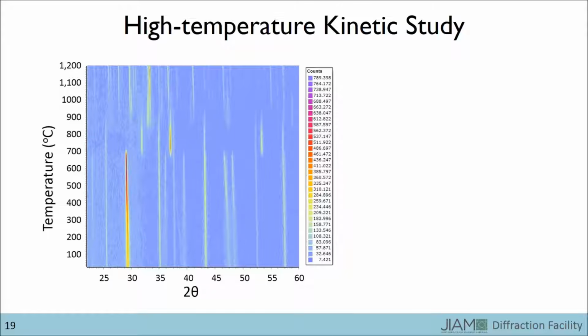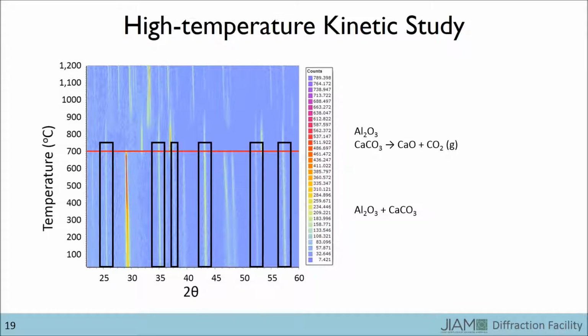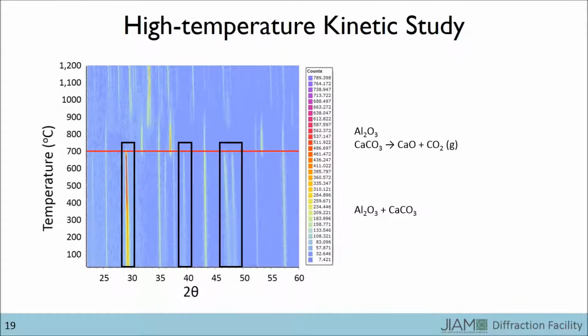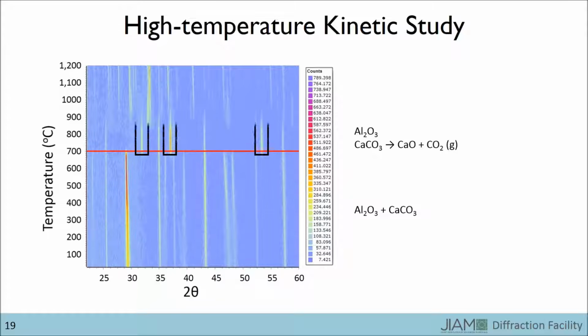In this experiment, the user began by mixing 2 materials, aluminum oxide and calcium carbonate, and pressing them into a pellet. That pellet was then placed in our system and data collection began. Once the temperature reached approximately 700 degrees Celsius, the calcium carbonate transformed to calcium oxide and CO2 gas, while the aluminum oxide did not react. If you look above and below the red line on the figure, you'll see some peaks continued from the lower region to the higher region. These are from the aluminum oxide. Some peaks ended. These are from the calcium carbonate. Finally, some new peaks appeared. These are from the calcium oxide.